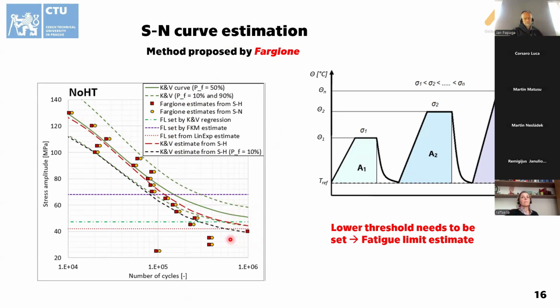But the problem is that I can start the test wherever I want with the amplitude of testing, and I can evaluate the stabilized temperature much lower than the fatigue limit. So what we need for the Fargione method is the lower threshold. So we need basically a fatigue limit estimate. Luca Corsaro already told you about the TCM method. We haven't applied it yet, but a similar concept is going to be presented here.